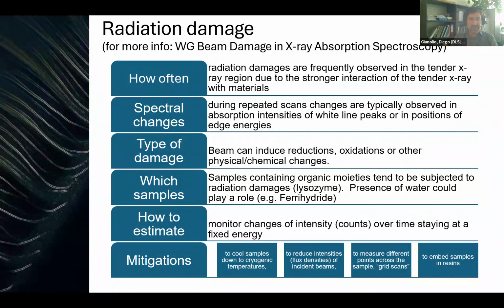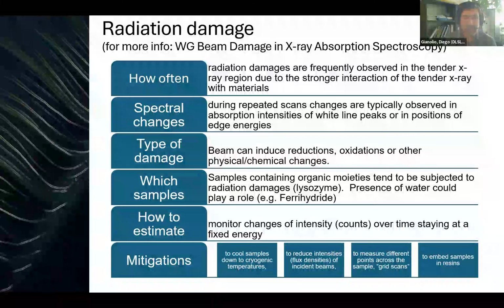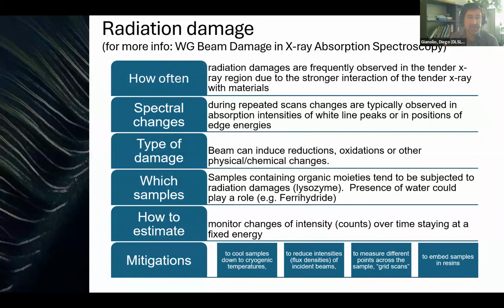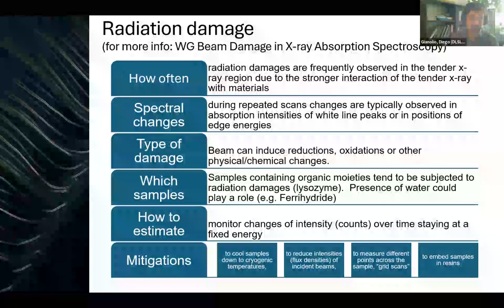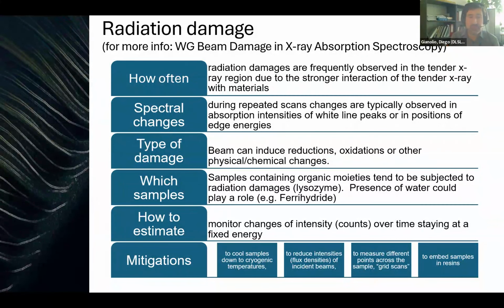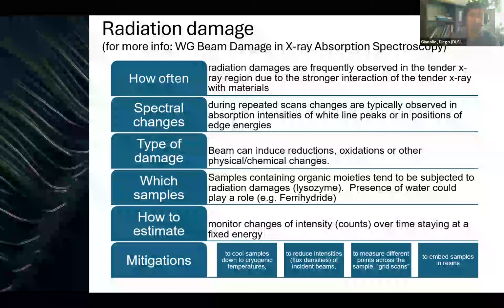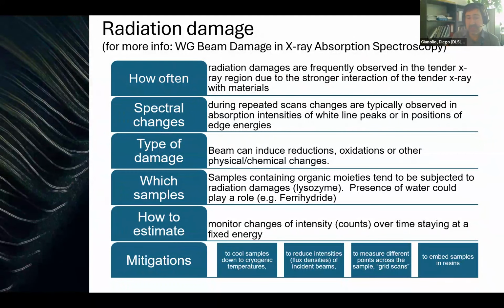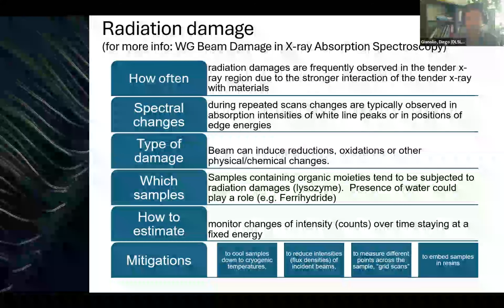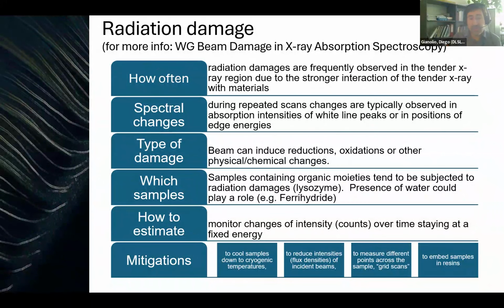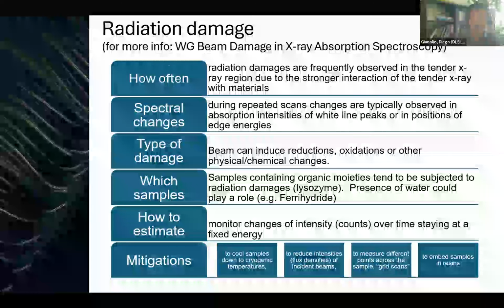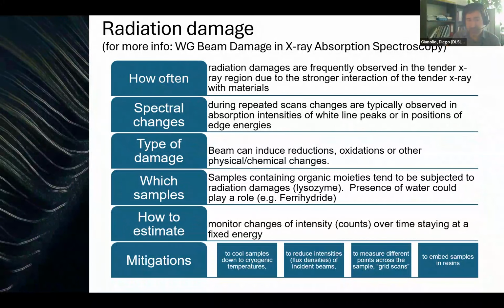It's frequently observed in the tender X-ray region due to the stronger interaction of the X-rays with the material. It shows as a change in the spectra. So if measuring multiple repetitions on the same sample, you can see changes in the intensity of the white line or position of the energy. The type of damage could be reduction or oxidation or other types of physical chemical changes. And normally we think that it affects more frequently samples that contain organic components.